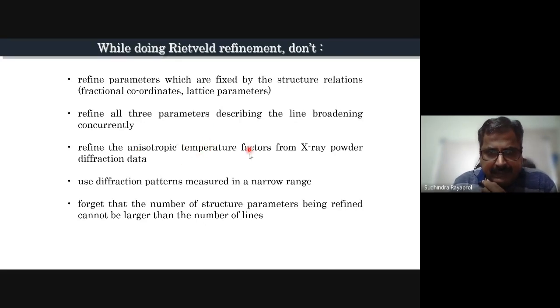In case of X-rays, in most cases, the anisotropic or isotropic temperature factor becomes negative, which has no physical meaning as such. So the best strategy is to keep it 0, or if you have the values available from the literature, you keep those values fixed. Don't assume that it can become negative and it is okay. Negative temperature factors have no physical meaning. And you should not use a narrow range of 2 theta values for refinement. You should use as broad a range as possible.